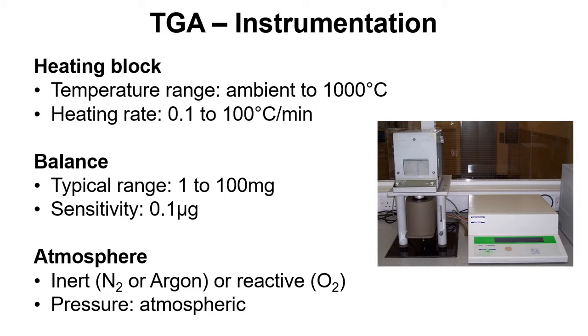Typical temperature range is ambient to 1000 degrees Celsius, although you can get specialist instruments that go to higher temperatures. Typical heating rate is from 0.1 to 100 degrees per minute.